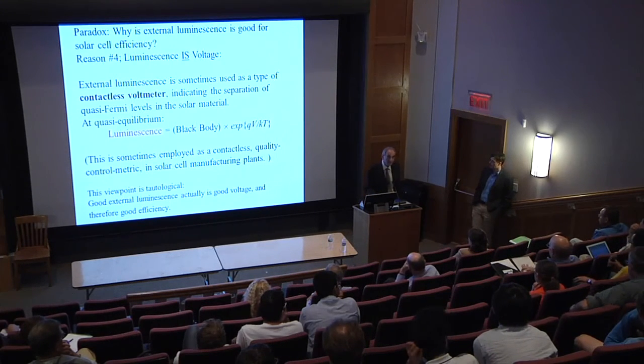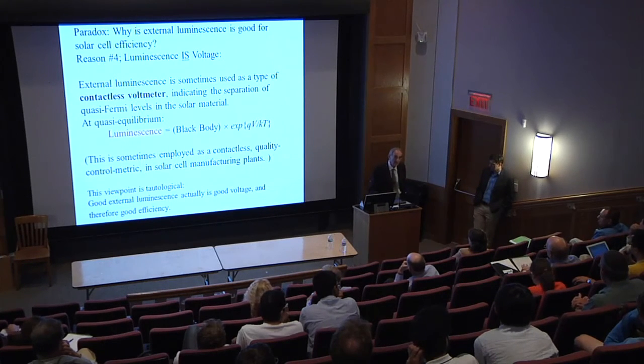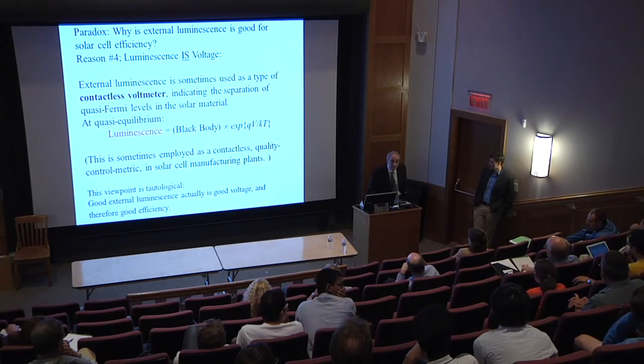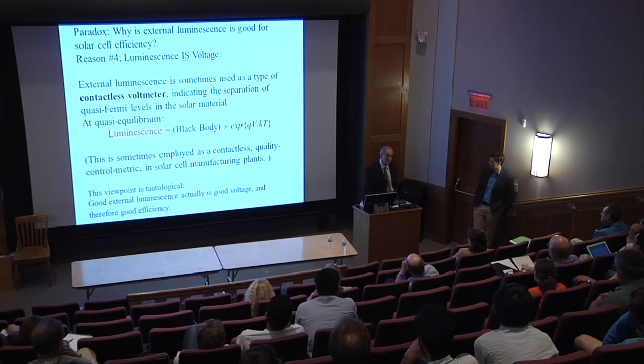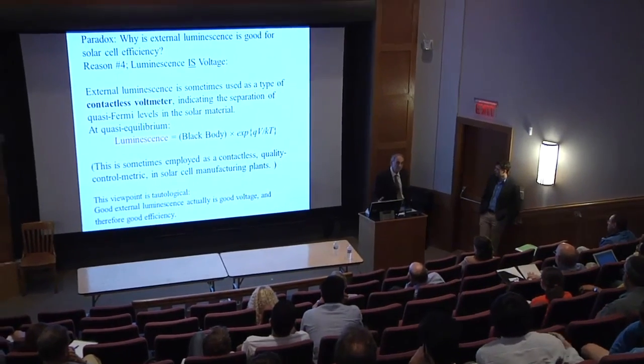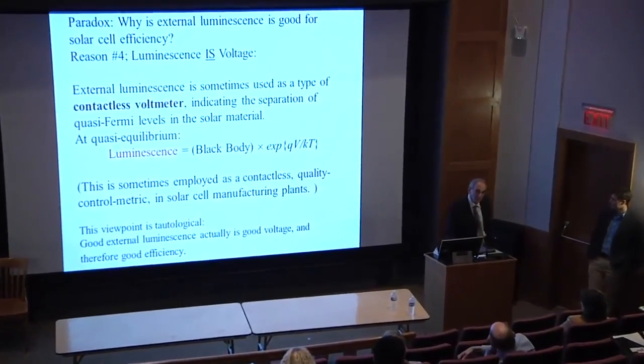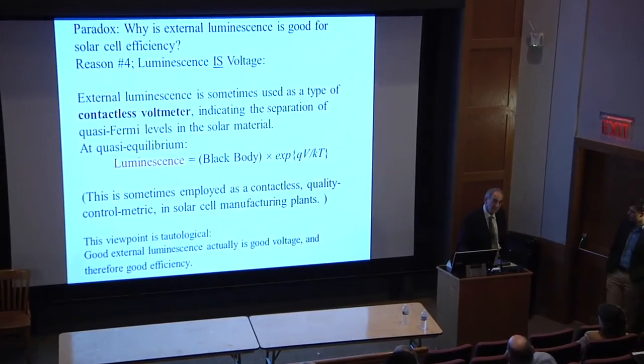Yes. Go on. So if you maintain a large quasi-Fermi level split inside the cell, that means you're not pulling out enough carriers. If you maintain a large quasi-Fermi level split inside a cell, then you're not pulling out as many carriers. Yeah. That's right. But this is for every solar cell. You have the open circuit condition where you get the biggest voltage. And what happens is that you give up a few kT of voltage in order to give the carriers a reason to go into the wires.